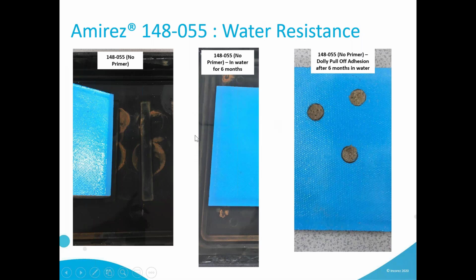And during the development, while we were starting to think about developing a top coat with those properties, when we checked the water resistance of 148-055, we actually realized it was really good and that it was still good after 6 months of immersion applied on concrete. So that was actually a block of concrete that was coated with 148-055. It was left there for 6 months, a bit forgotten. And then when we moved it out and checked it with the dolly pull, we realized the adhesion was really good. So that's where the all-in-one comment is coming from.